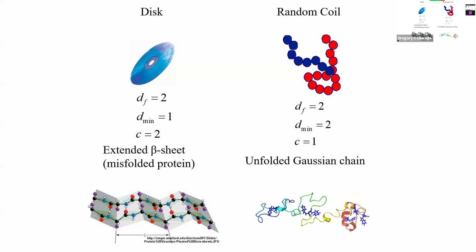So yeah, the other paper I've been looking at is on fiber stretching in extensional flow, which is like if you take two plates and stretch them apart and you have goo between them, like glue, and then you stretch it out and the chains are getting stretched out, right? That will definitely affect the chain size, and the models say that it affects the chain size. So the chain size will increase with tensile force. So what you have is dF will drop to 1.